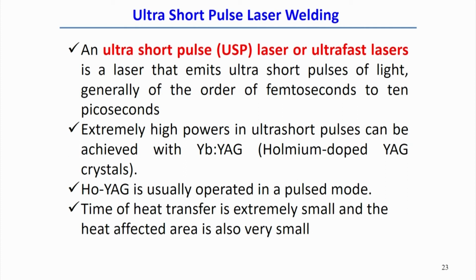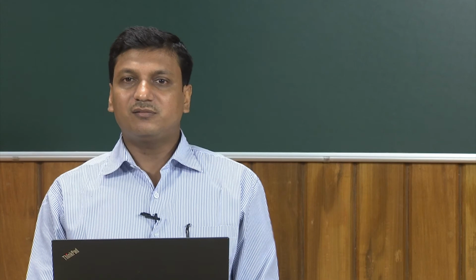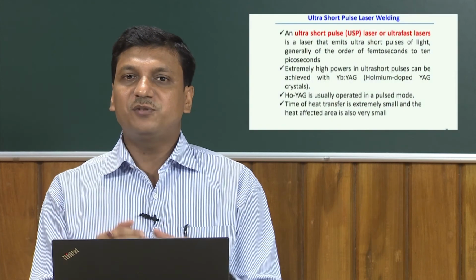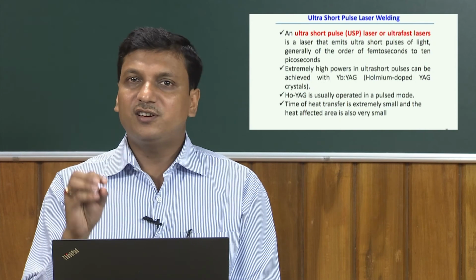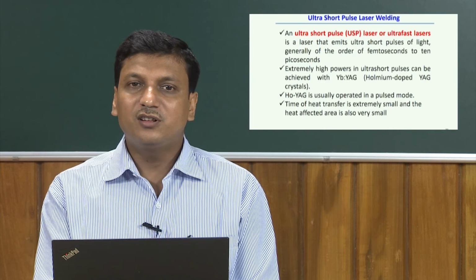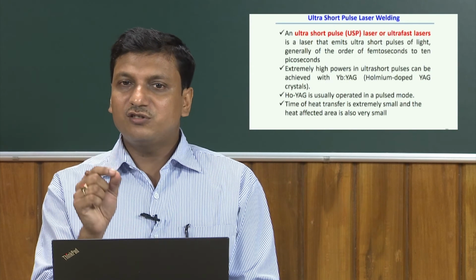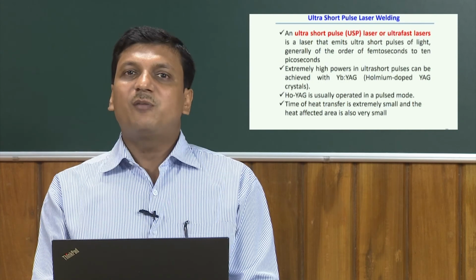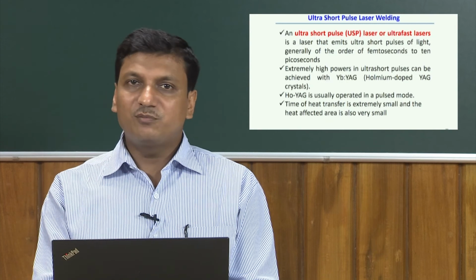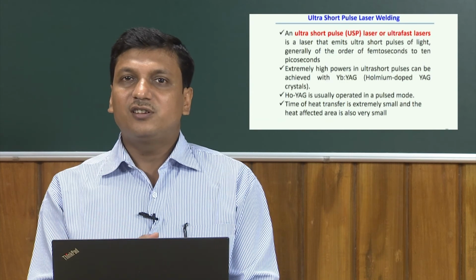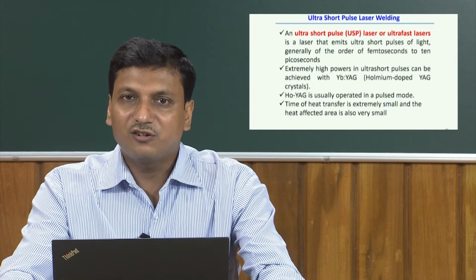The ultra short pulse laser, sometimes called an ultra fast laser, is a laser that creates pulses over a duration of the femtosecond to picosecond level. Since the pulse duration is very small, we can create very high power with a low amount of pulse energy. In principle, the ultra short pulse laser simply applies the pulse energy within a very short duration of time. That pulse duration is comparable to the relaxation times within metallic material, and also other non-metallic material.